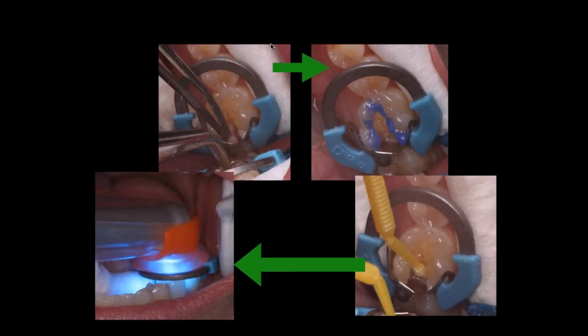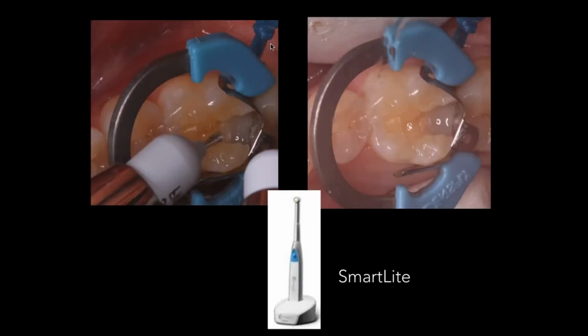We're going to apply that for 20 seconds, followed by a nice thin stream of air for approximately 2 to 3 seconds. Again, you don't want to have any kind of rippling. You want to make sure that it's completely steady and glossy, and then light cure that for 10 seconds. Again, look at that semi-gloss appearance, and then you know that you're ready. I've got that light completely on top of that restoration, finger rests, and properly curing it.